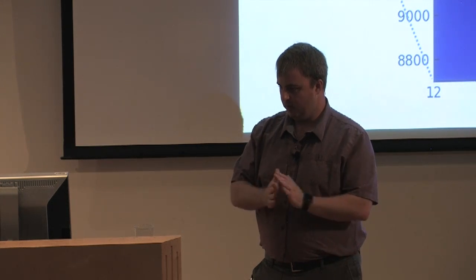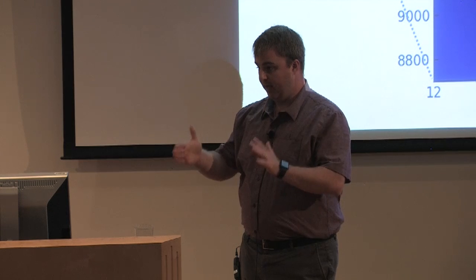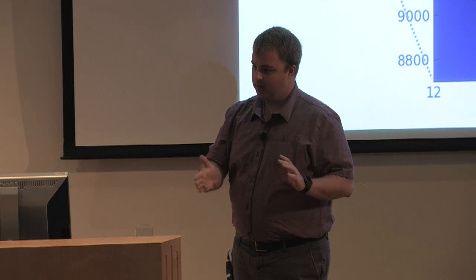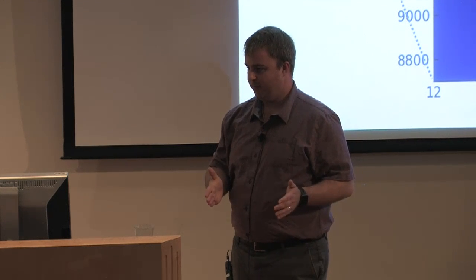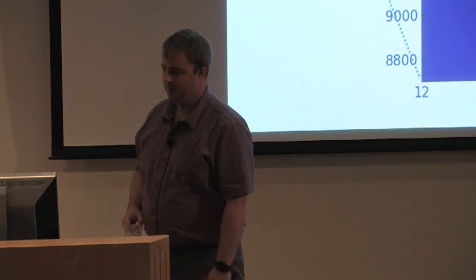So if you have things in the sample that give you a broader peak, what you measure is a convolution of that and what the instrument response would be for a perfect sample. And so you can try to deconvolve those. For something like the footprint correction, it's difficult because it's basically a top hat shape. So really what you try to do is minimize it by playing with the geometry of the measurement as much as you can.